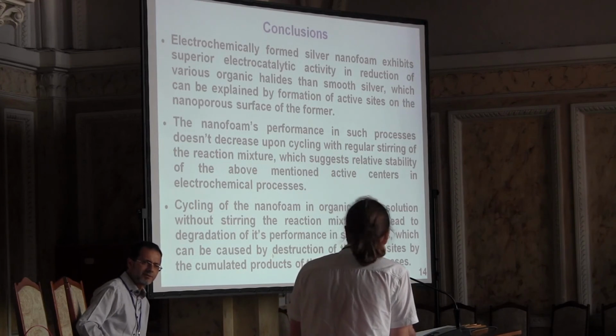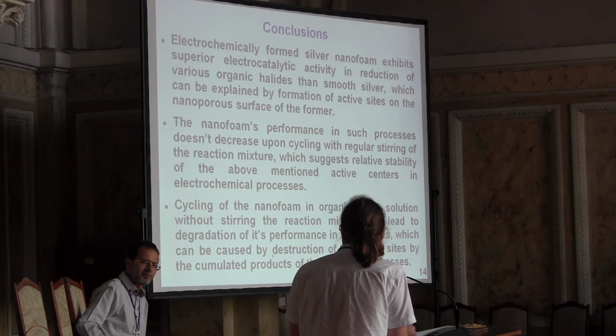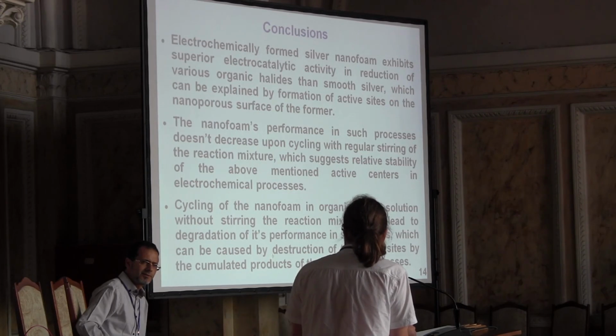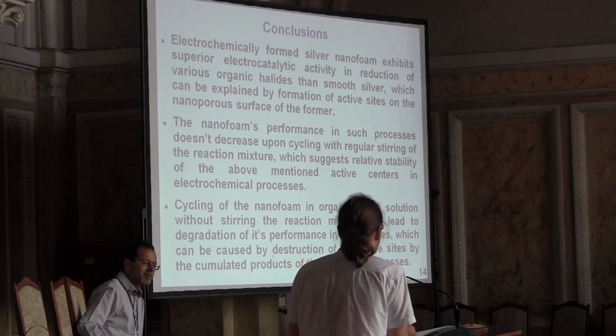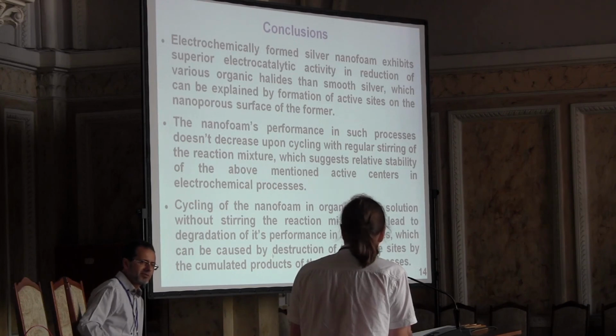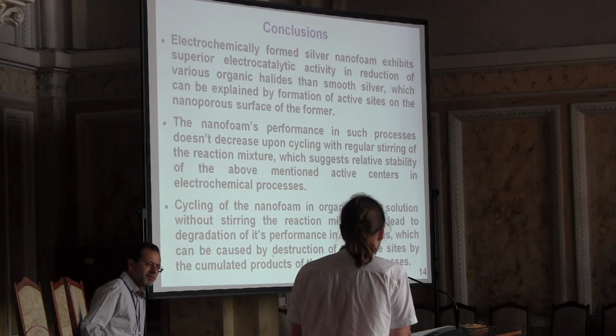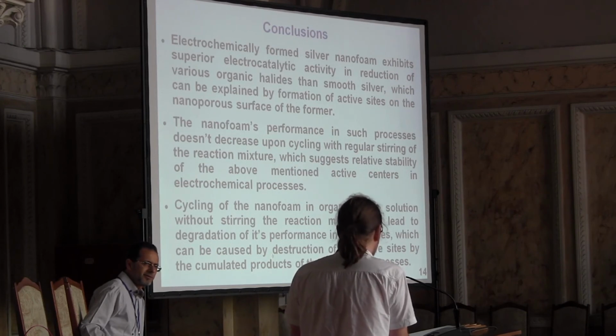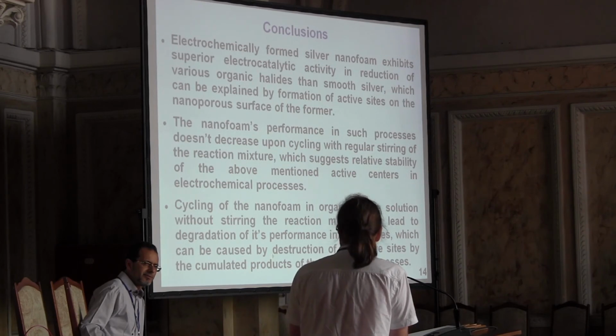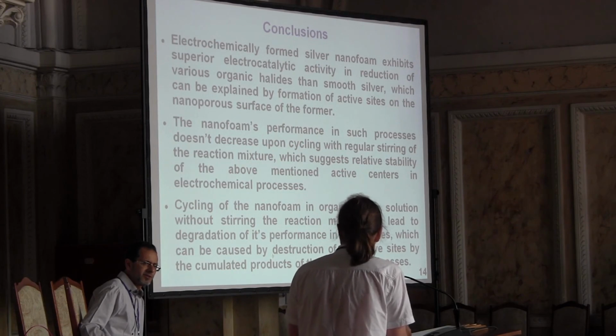We provided electrochemical measurements. We estimated the capacity of double layer from cyclic voltammograms at different scan rates and compared it to the smooth silver surface. We didn't provide other techniques such as gas volumetry. We got a small amount of this material, so it was very difficult to make other measurements.